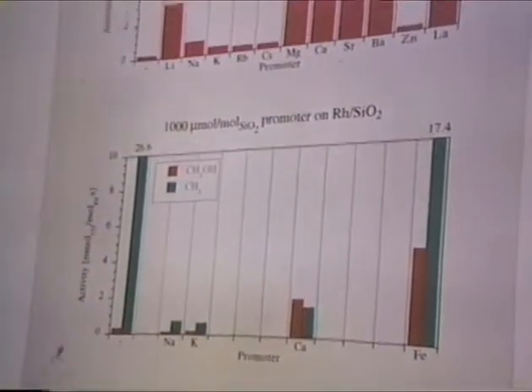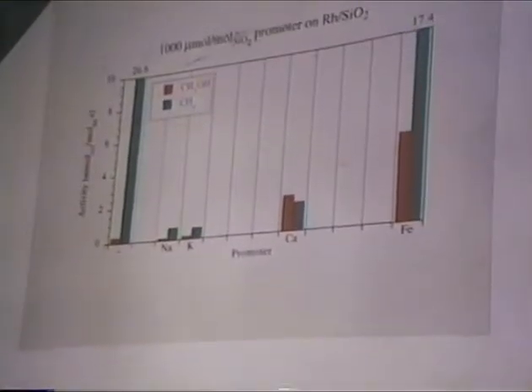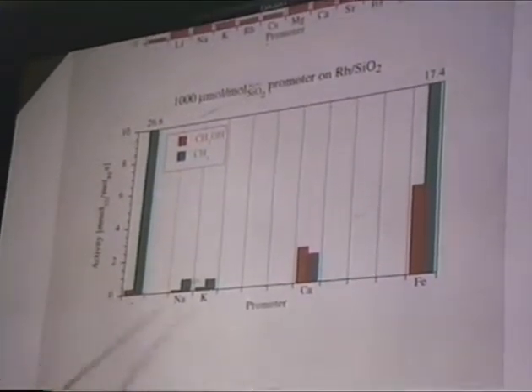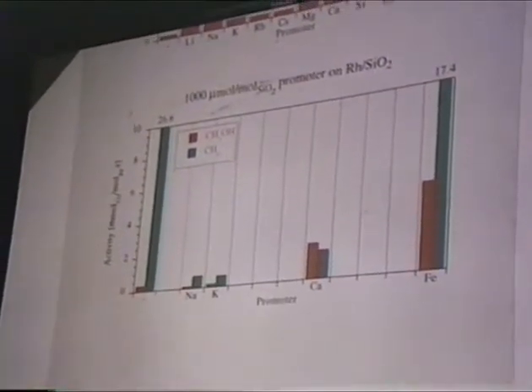When you look at a few results for rhodium that we have, we didn't study that in such great detail as the palladium. Originally, without any promoter, the methanol is low, there's a lot of methane. When you come with something like calcium, you go to more or less 1-to-1. As I showed you, you also promote the methanol in this case, but depending on the loading, this loading was not very high, you can't suppress the methane very much, and the sodium and potassium are no good.